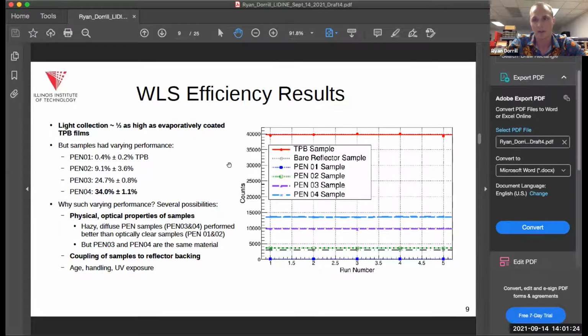So here's the performance, and the reason I list all those samples is because you'll see there was somewhat widely varying performance between the samples, from very low up to as high as 34% relative to TPB. So pretty good, but this raised some important questions, such as why do all these samples perform so differently? And also, are samples 3 and 4 essentially the same material? Why did they perform so differently? We had some hypotheses, including the physical and optical properties of the samples. Samples 1 and 2 were essentially clear with some small differences, and then 3 and 4 were essentially hazy. So you could see differences.